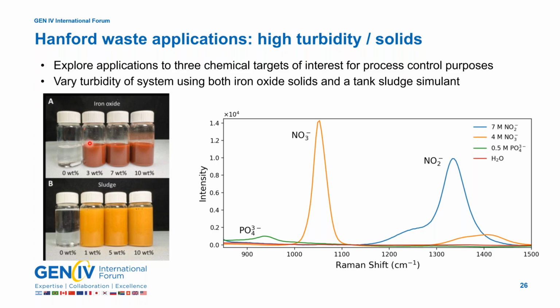The picture on this left-hand side shows a series of solutions. This is our simulant waste here, with 0% solids added, and then we add, in this case, iron oxide. We have 3 weight % solids, 7 weight %, all the way up to 10 weight % solids, very turbid solutions, and would present a problem for light scattering in an optical technique like Raman. Down below, we have a simulant sludge. In fact, the sludge was designed by some of our colleagues at Savannah River National Laboratory. And again, starting with our simulant waste with no added solids, all the way up to 10 weight %, you can see highly turbid solution.